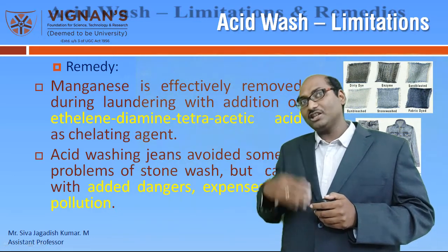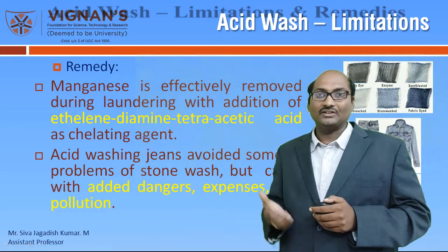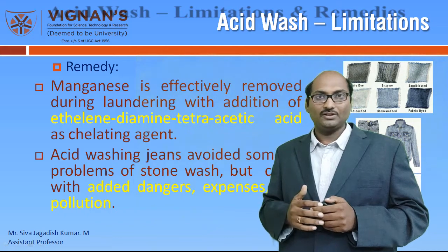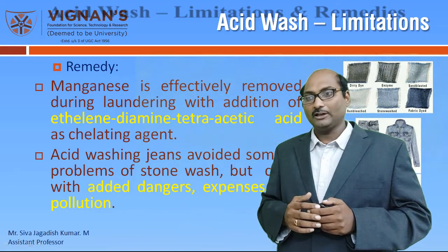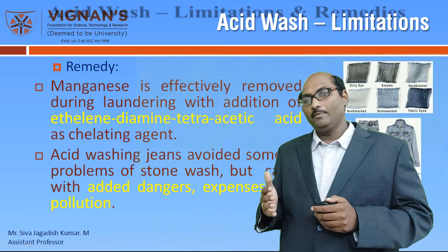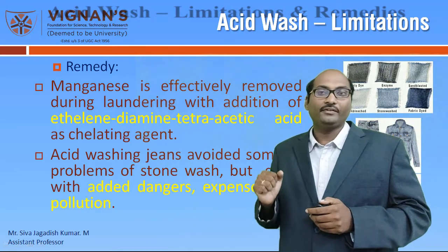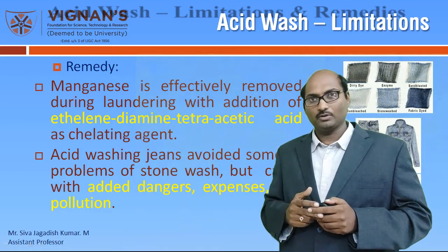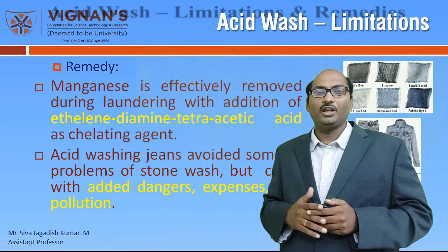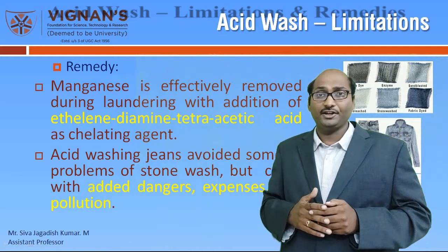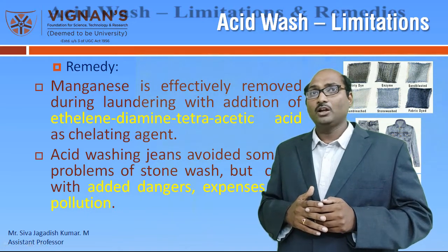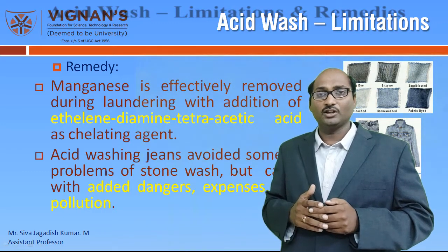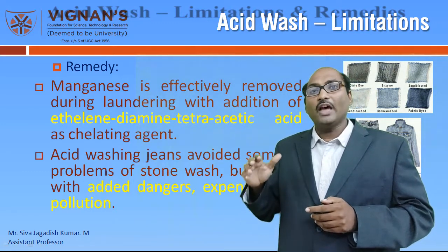But additional dangers, additional expenses, and additional pollution came into the system. These are some of the limitations and remedies. One problem is the color staining, the yellowing, which can be reduced by adding EDTA, ethylene diamine tetraacetic acid.